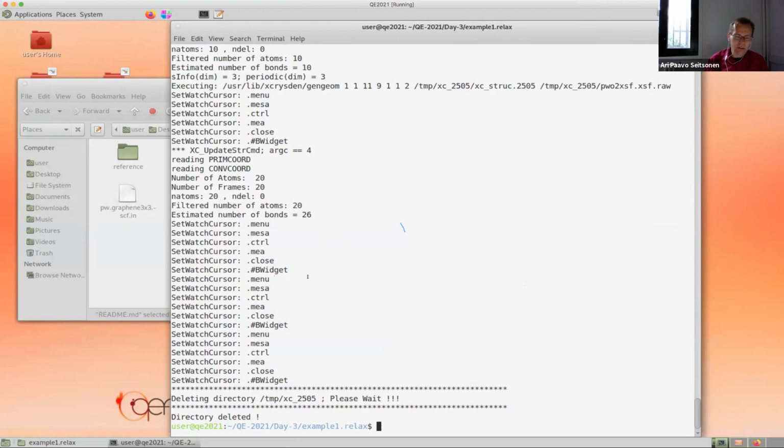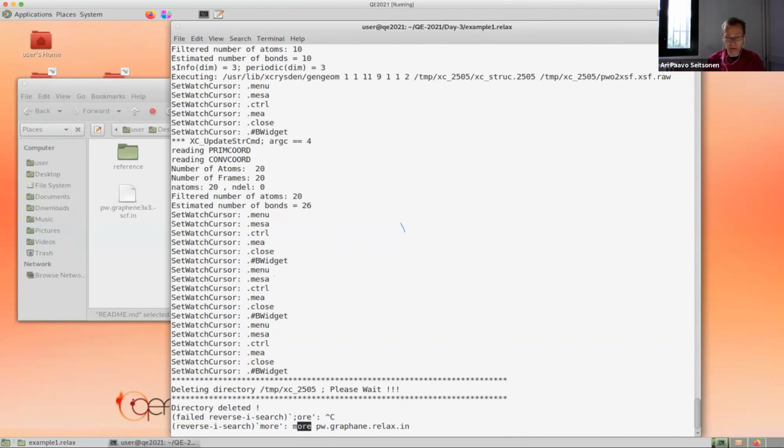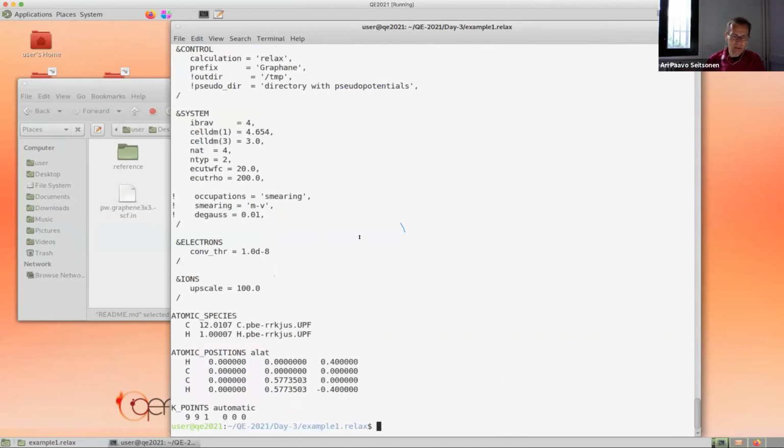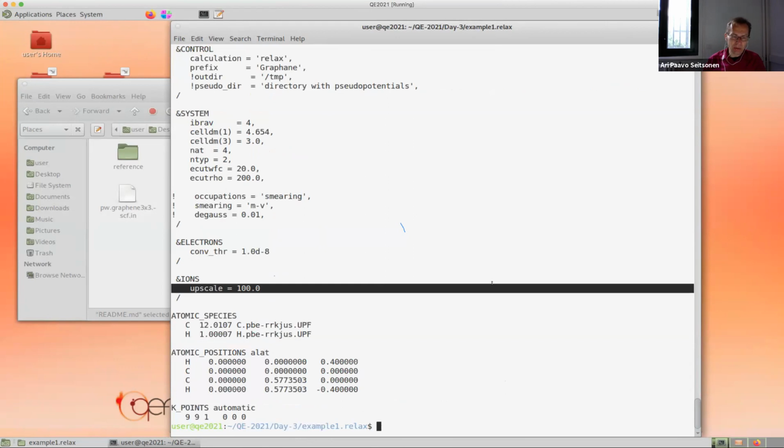Yes. So you can try to make the steps, at least the initial steps, smaller. If your structure keeps taking many BFGS steps, and it looks like the structure is not converging, then you can try, for example, to reduce this upscale parameter. I checked, and I think 100 is actually...